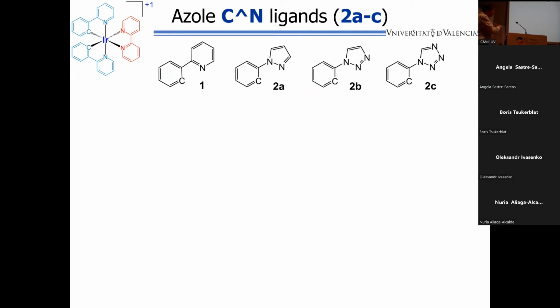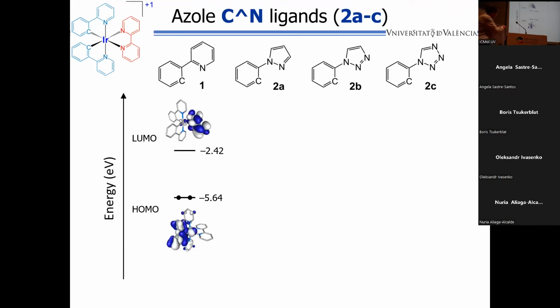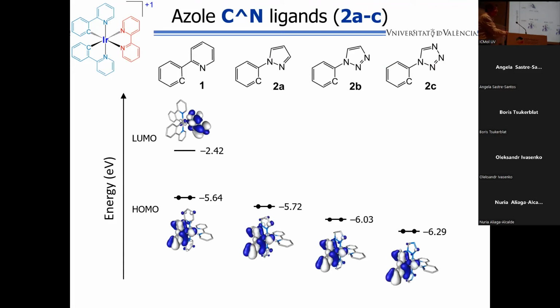Look, in this video you have the archetype complex we are using as a reference, and we are changing the pyridine ring by an azole ring with an increasing number of nitrogen atoms. Okay, here you have the HOMO and the LUMO of the system, and when you put the azole and you start to increase the number of nitrogen atoms, you are stabilizing the HOMO very nicely.